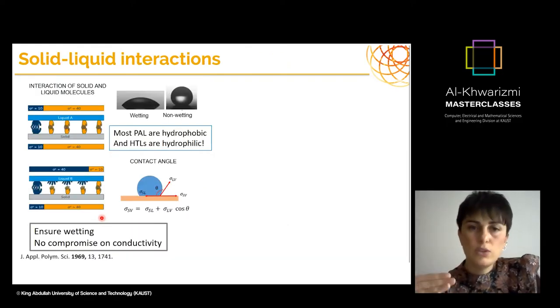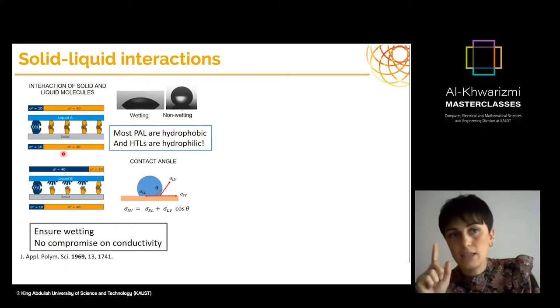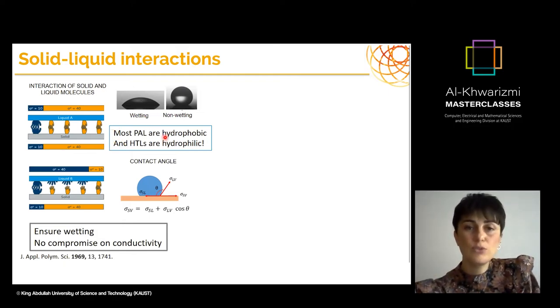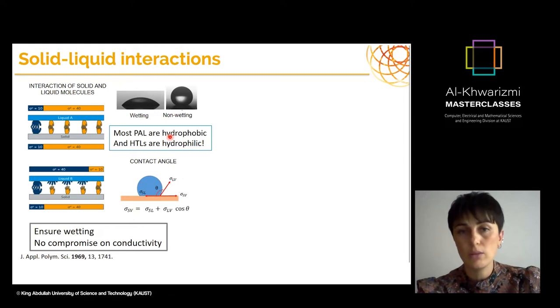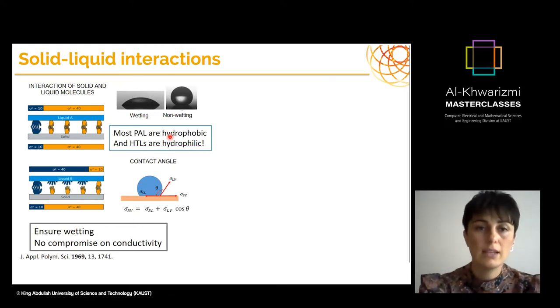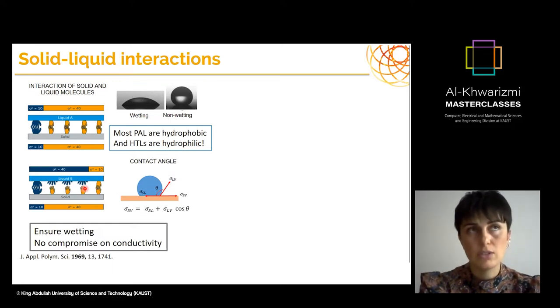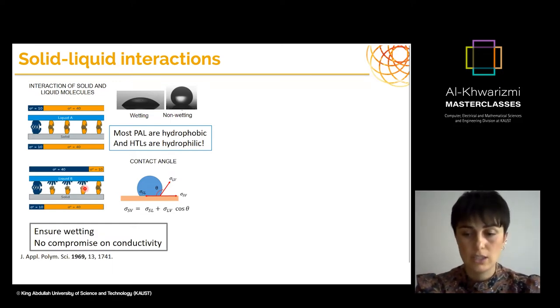So as I said, because we're looking for a hole transport layer that is going to sit on the photoactive layer, we need to understand the interaction of the two layers. One interesting fact here is most of the photoactive layers are hydrophobic because they're polymers and small molecules, and most of the hole transport layers that are sitting on top are really hydrophilic, such as PEDOT:PSS. So how can we ensure wetting between these two non-compatible materials and also not compromise on conductivity, because it needs to extract the charges?